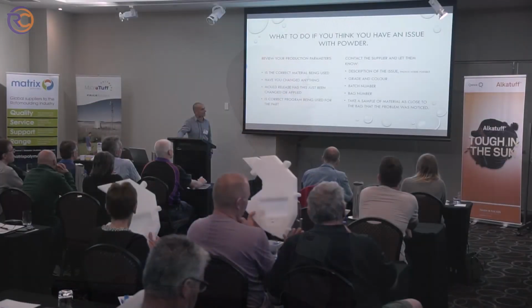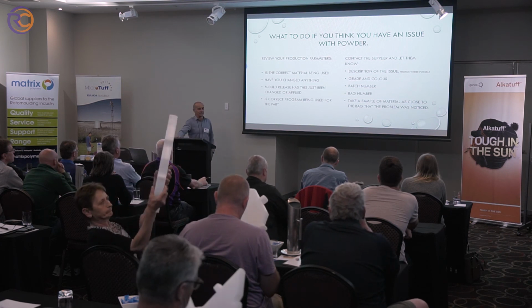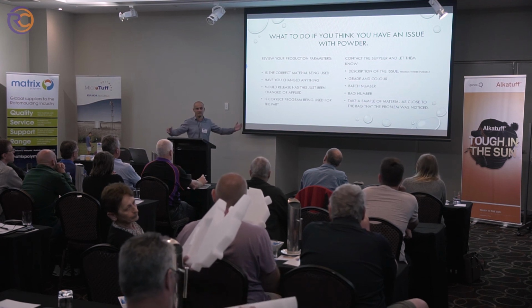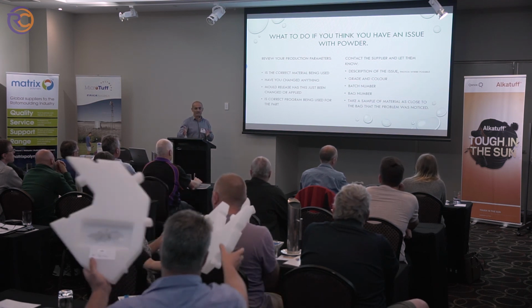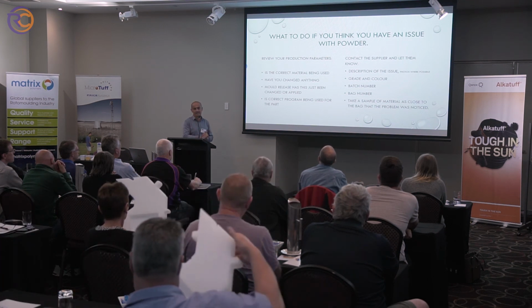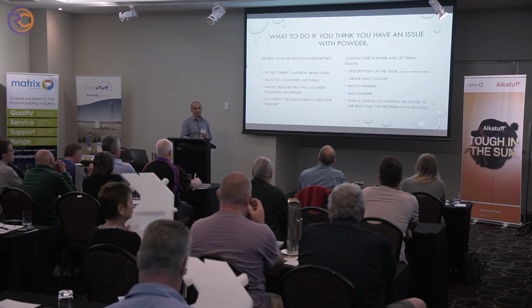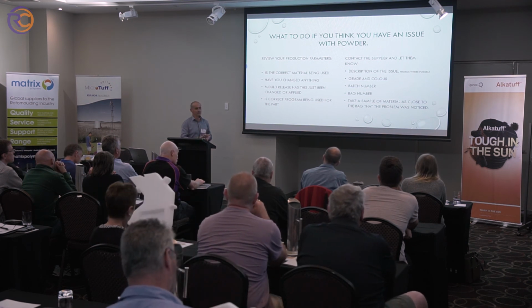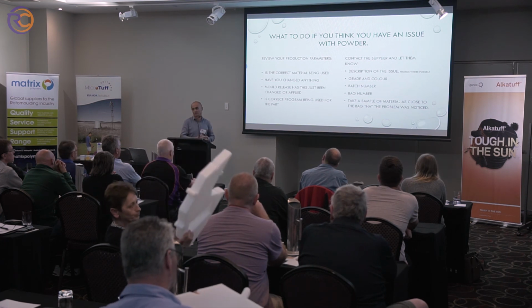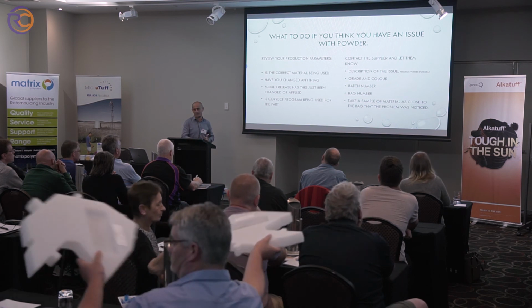So if you have had a look at everything, and you still have a problem, you do need to contact your supplier. A really good way of letting us know what's going on is to send us a photo, and it's really easy. Just on your phone, take a photo, send it by text or by email, and always tell us, obviously, the grade and the colour. Batch number is really important, but the bag number is even more important, because in a run of material, we can do a 1 tonne run or we can do a 50 tonne run. So where in that 50 tonne run is the issue? The bag number is really important, and what is really good is if you can take a sample of half a kilo or a kilo of the material close to the actual issue and send it to us or to your supplier, and we can check that powder and find out what's going on.